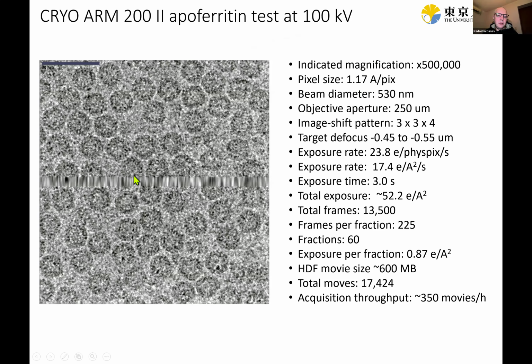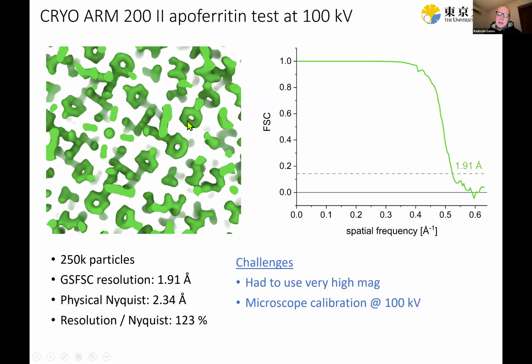You also see here the gap in the middle that is interpolated in software after the data is collected and is being processed. And another thing is that in cryo-EM, when a particle is close to the edge of the image, it typically is not usable because part of the information is delocalized due to defocus outside of the image. So you can see from this example image that not very many particles will be usable from this kind of image. So hopefully future generations of these detectors will be gapless in the middle, so that at least the central portion is not sacrificed. This dataset reached 1.9 angstrom resolution, 1.91, with 250,000 particles.